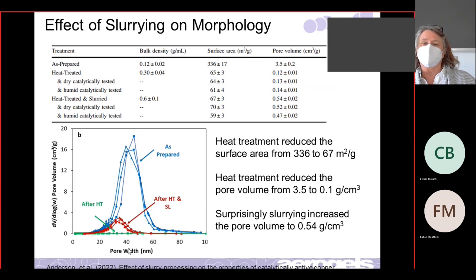When you heat treat them, look at this down here, nothing. On this scale, there's nothing. You don't see any peaks. The surface area drops to 65, which is not unusual whenever we heat treat any of our materials to that high temperature, except for the silica.